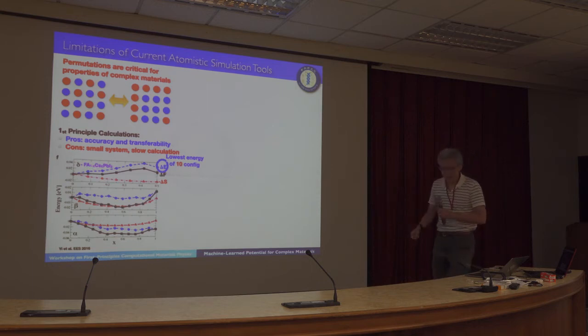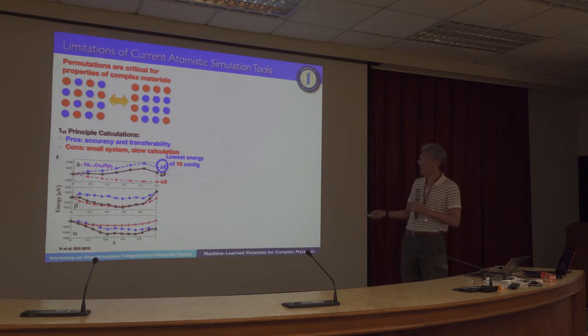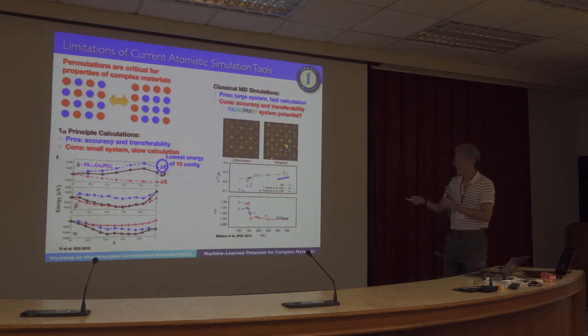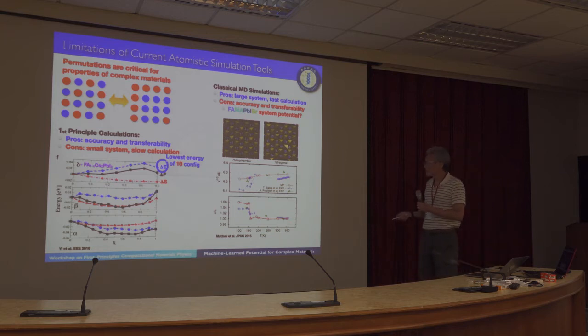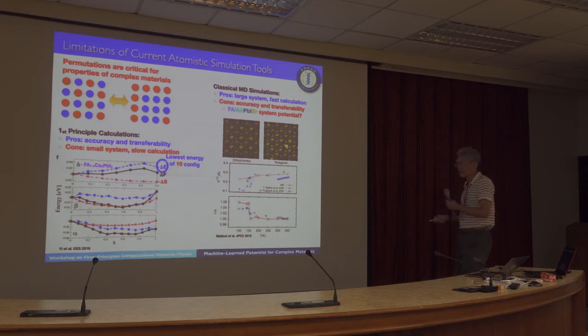So this sometimes is not ideal, because for this material you can have many possible permutation ways, and only 10 sounds like too little. However, that's the best that they can do because of the limitation of first principle calculation. And the other possibility is to use classical MD simulation. Of course you can see that classical MD can deal with a very large system like this, and it's very fast. I know that for some of the computers, like the DE Shaw computer, if you spend 1 month, you can compute the MD for like 1 millisecond. Yeah. But however, the problem is accuracy, especially for a complex system like the perovskites.